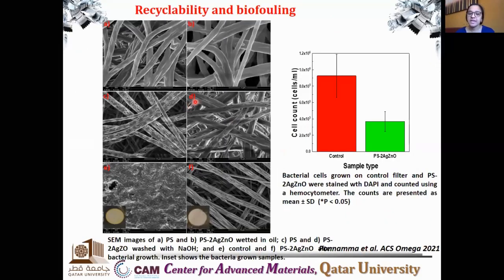And these are the different SEM images. These SEM images show the cleaning capability. After the oil water separation, what do we have to do for the fiber? Each time we have to rinse the fiber in sodium hydroxide or any surfactant medium so that the oil will be cleaned out of the fiber. So we monitored the fiber by SEM before and after the cleaning, and we found that it is working well. The membrane is recovering its own structure after the cleaning process.